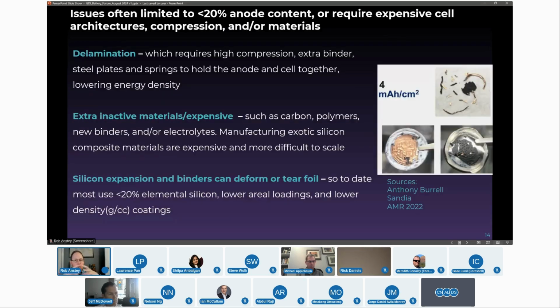Now, why is it so difficult? Why is no one going above 20%? The main reason no one's going above 20% in a powder-based system is it literally rips your foil to shreds, or it delaminates, or it does both, or it causes issues with your binder system. And that's sort of limited commercial state-of-the-art cells. Now, I've heard that there are some people getting it a lot higher with silicon carbon composites.